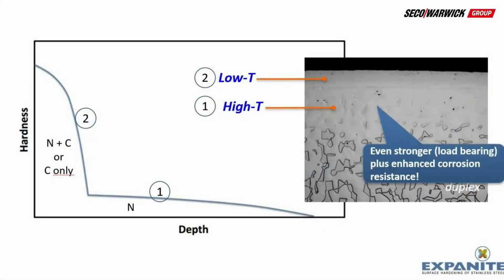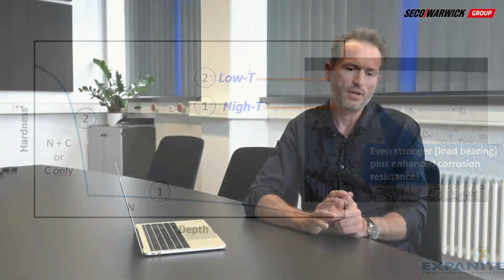And please don't mistake it, it's not an annealing, because annealing would just make things very soft. We are compensating for the hardness loss by introducing nitrogen. So we are gaining some of the lost hardness in the surface by the nitrogen content from the high T process. Combining those two processes, we get the Super Expanite, and this is really the most offered process. I would say 80% of what we do is Super Expanite, and it's used for many things.